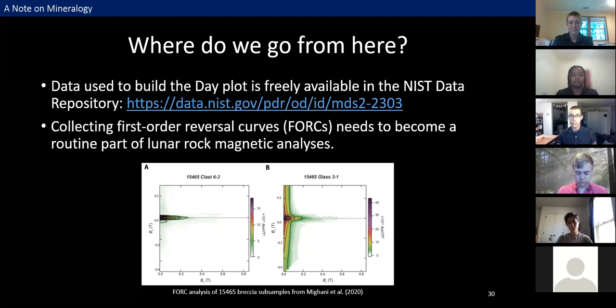The clast on the left has this horizontal ridge that extends to fairly high coercivities, and that suggests the presence of single domain and pseudo single domain grains, which are quite small. While the glass on the right, in addition to that central ridge, also has this cluster at low coercivity values, and that suggests the presence of larger multi-domain grains. And I can tell you all of that totally independent of a day plot, which is pretty cool.